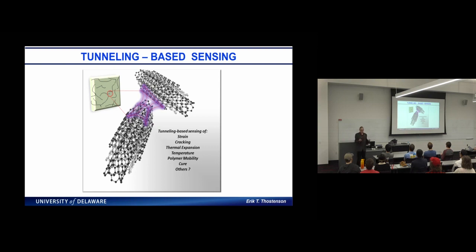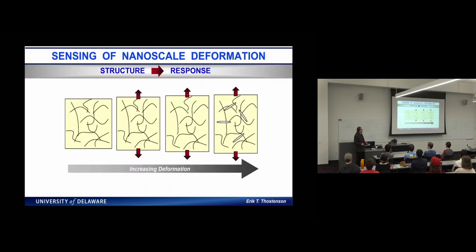So if you stretch it or heat it or whatever it might be, this region where you have the electron tunneling, that contact resistance changes and enables this sensing. This is what we call a piezoresistive material. Piezoresistive means that with a strain gauge, if you stretch a conductor, the change in electrical conductivity that you measure is this change in the length and then also the Poisson contraction. But in this case, when we stretch it, these tunneling gaps change. Even though that resistance change might be very small at that level, we're adding it up over thousands and thousands of individual contacts. So this is really the mechanism.